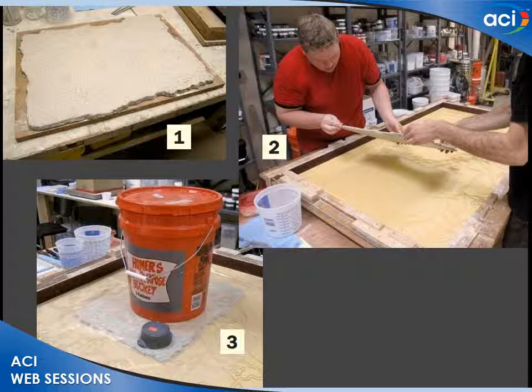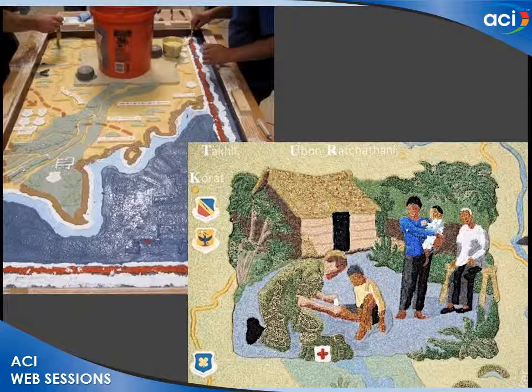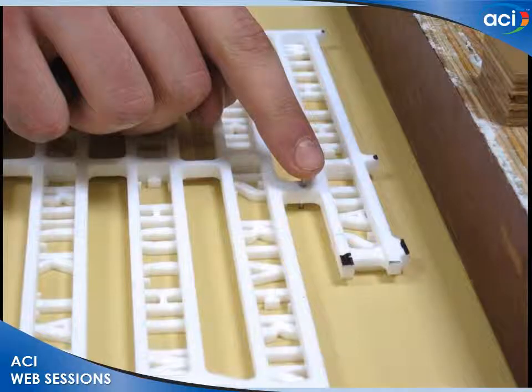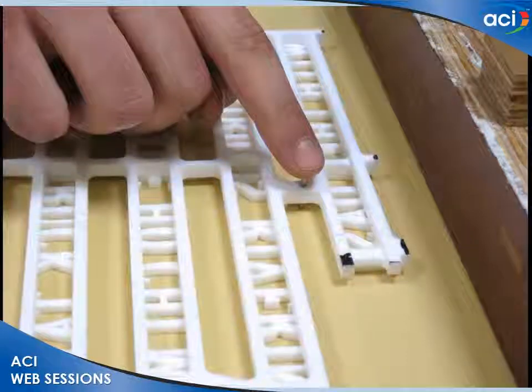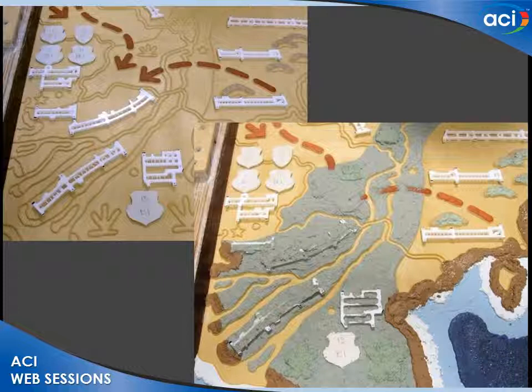Then we put a natural clay on the face of that panel, laid it into a pocket in the mold, kept it flat and moist while we placed all the other materials around it, and when we exposed everything, it was flush with the face and it looked like it had been placed originally. We used stainless steel pins for registration of all the letters, so we had holes in the letter acrylic grid and in the mold. And then we had pockets we machined in the mold to fit the porcelain inserts to hold them in registration.